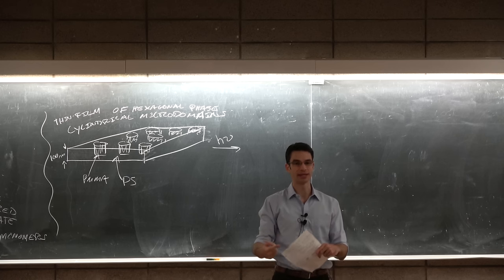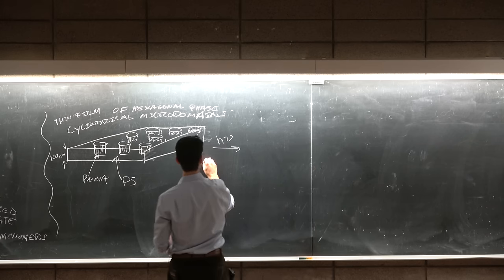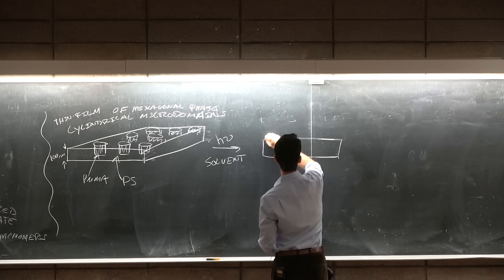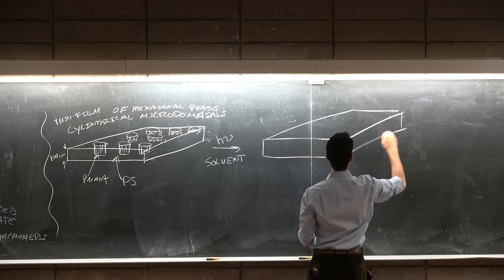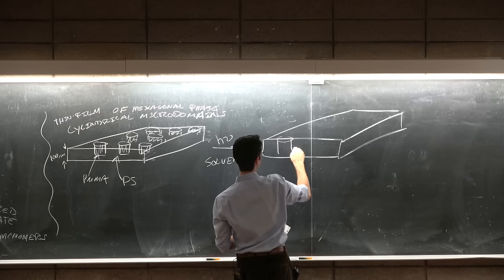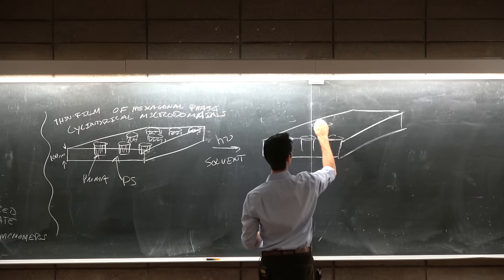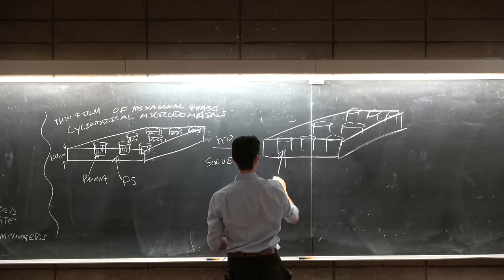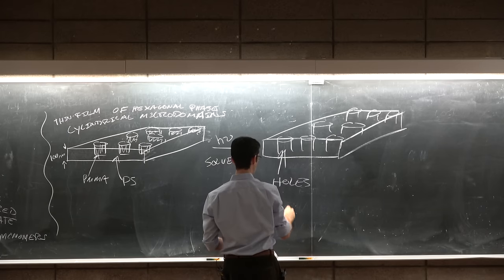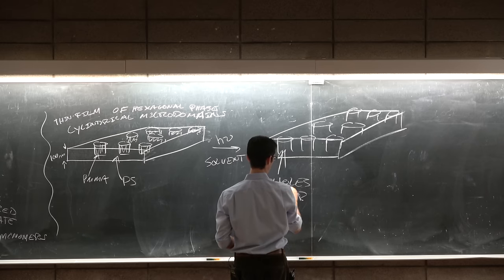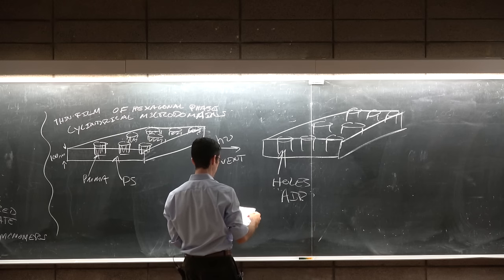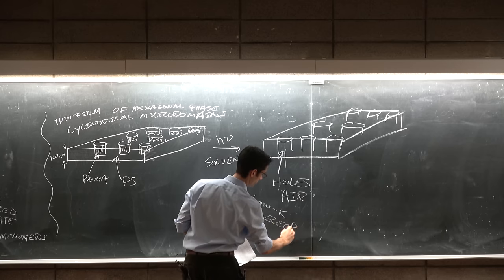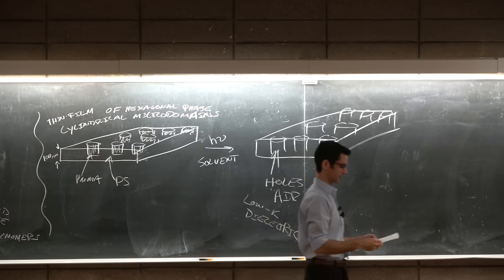And what's cool about PMMA is that you can etch it out by exposing it to UV light or an electron beam. You degrade it. And then you can wash it out with a solvent. So now instead of cylindrical microdomains, you have holes. Or instead of the cylindrical microdomains of PMMA, you now have holes. There are holes filled with air. And this slab is now a low K dielectric for transistors.